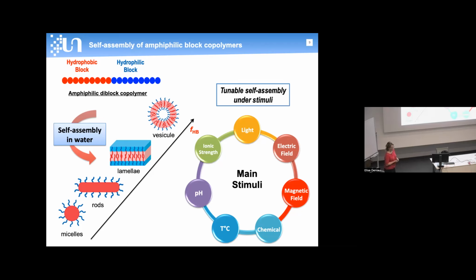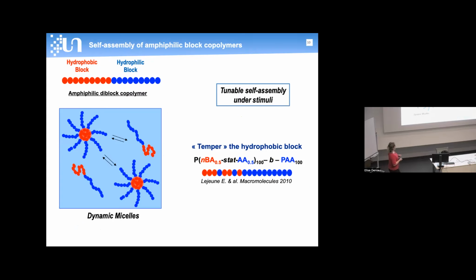And what is interesting with this system is that you can tune the self-assembly with different stimuli, depending on the chemical nature of the polymer units. And what we know since the PhD that I did in Le Mans with Christophe is how to form a dynamic system, dynamic micelles, meaning that there is a reorganization between the micelles via exchange of single unimer chains. An interesting way is to incorporate hydrophilic units in the hydrophobic block in order to decrease the surface tension between both blocks, and thus forming reorganization of the micelle.